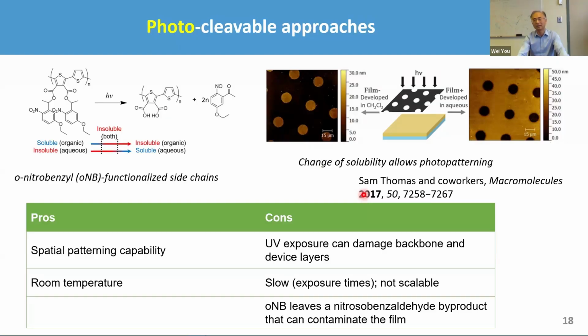And then Sam Thomas and his lab are using this approach. They're able to use photolithography. So this is the one thing good about using photocleavable, because you can do lithographic patterning of the materials as you want. Use room temperature as well. But now, in many cases, if you expose your conjugated polymer to UV light, keep in mind you have double bonds, and these bonds are easily susceptible to UV damage. So then you end up with bad material, damaged material. That's not good for your performance if you're going after optoelectronics. And it's also a very slow process with a long exposure time. And then again, you will be running the risk of damaging your film.